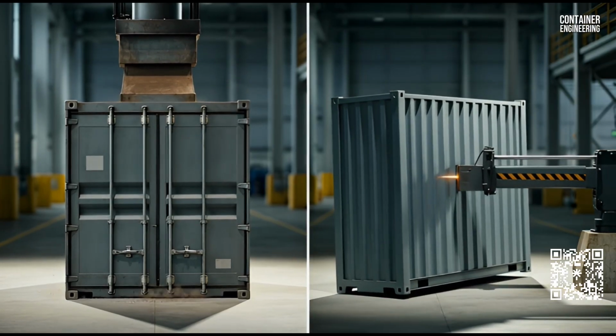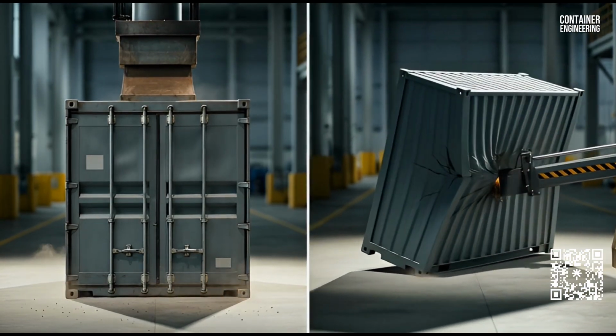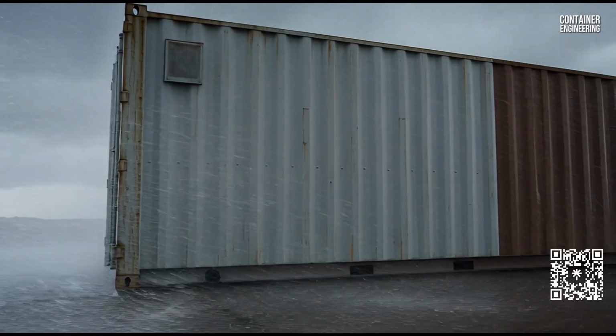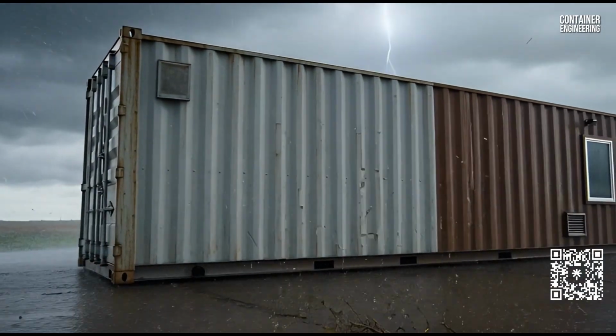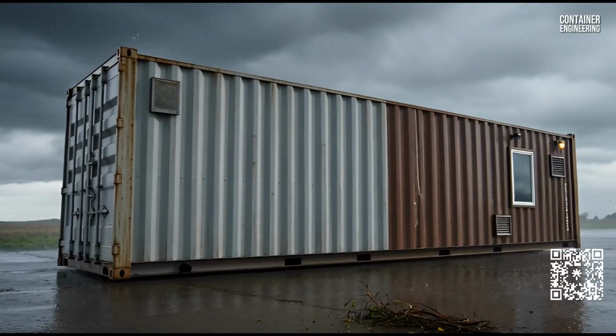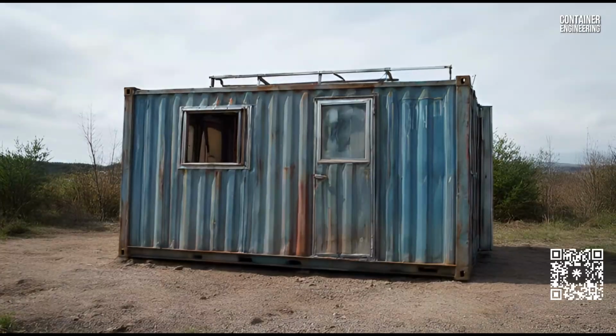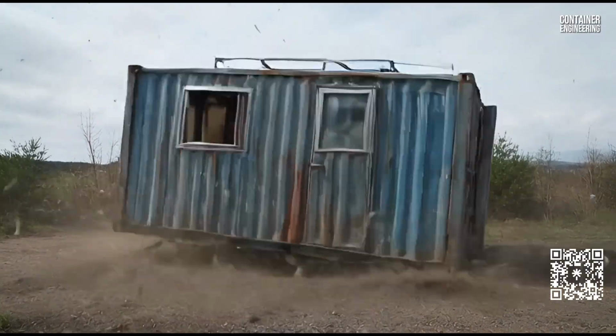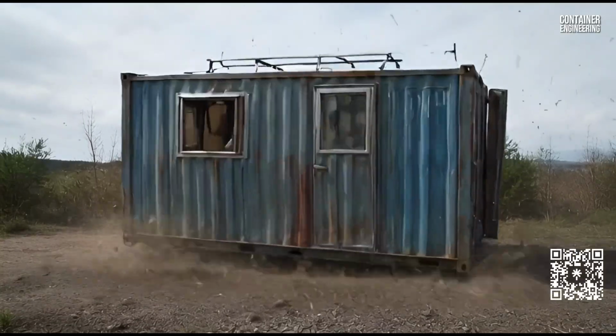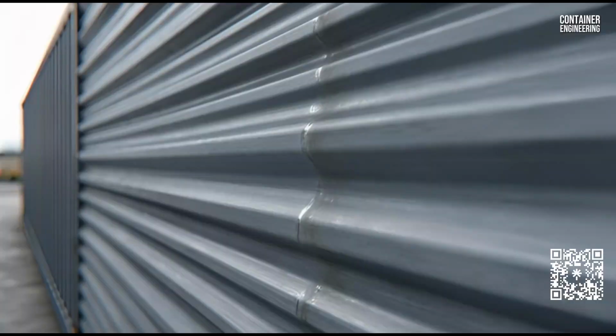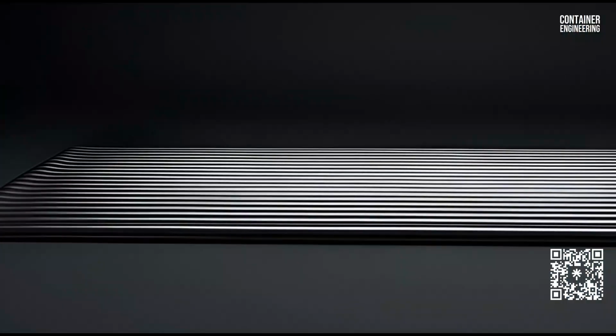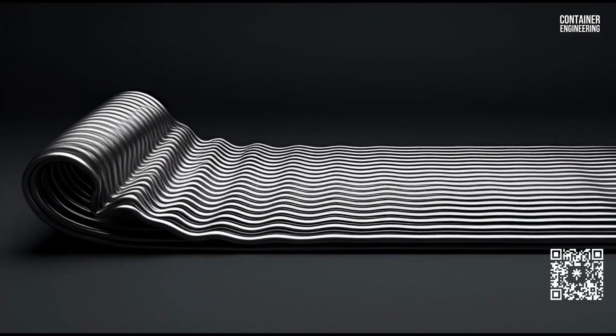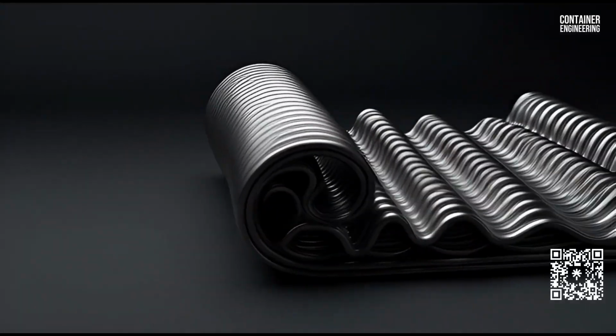6 months after construction, they had a 60-mile-per-hour windstorm. The container twisted 4 degrees along its length. 4 degrees doesn't sound like much, but over 40 feet, that's nearly 3 feet of horizontal displacement at one end relative to the other. Every door jammed, every window shattered. The interior framing separated from the walls. The container was structurally compromised and had to be demolished.